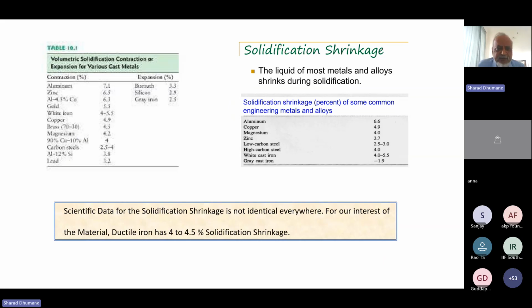Okay. So in this slide, I have just given some references from literature, the solidification, volumetric solidification shrinkage. So the table on the left side gives volume of solidification shrinkage for different cast metals. For aluminum, it is 6.1. For zinc, it is 6.5. Sorry, aluminum, it is 7.1. Zinc, 6.5. Aluminum, copper, 6.3.